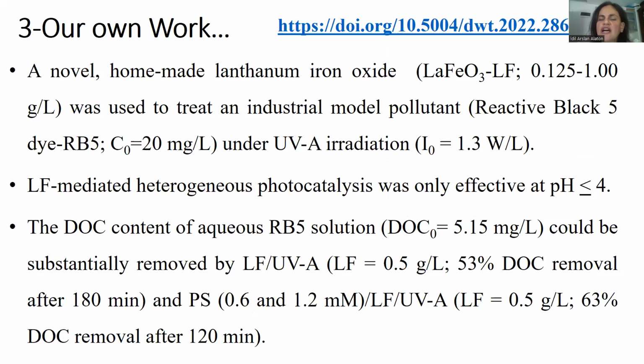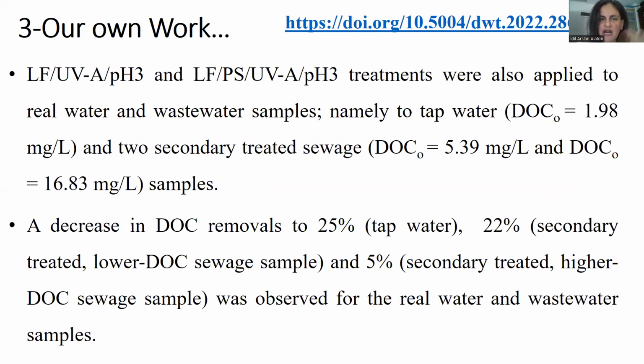Then would like to finally show you a more recent study. A homemade lanthanum iron oxide was used to activate peroxydisulfate. As the industrial model pollutant, we used reactive black at a higher concentration because we wanted to mimic the dye-house effluent and UV radiation. The DOC content of the reactive black solution came from the dye stuff, but we also tried different water media here. And so we added persulfate to the lanthanum iron oxide (LF) UV-A photocatalytic treatment, and we just observed a dramatic increase in the oxidation rate.